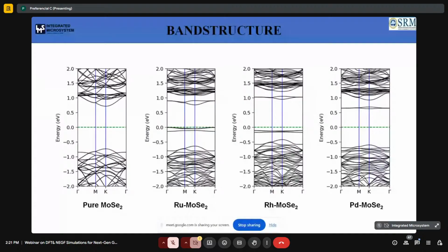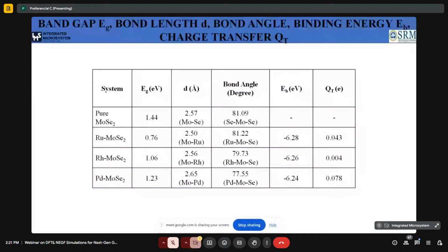And these changes in the electronic structure, which have happened when the dopant is attached or incorporated with the system, involve a charge transfer between them, and the changes can be observed by means of the charge transfer analysis. So here we have observed a positive charge transfer value, and this positive value represents that the dopant acts as a donor and the system is acting as an acceptor.